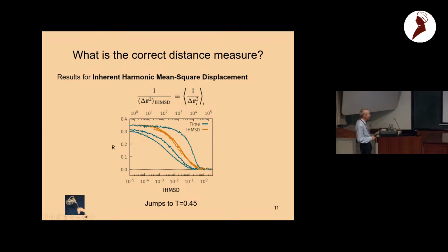And these blue curves are the normalized relaxation functions, and they collapse pretty well if we use this distance measure. There is a mathematical inconsistency in the distance measure, but I don't think it's a serious problem. If you interchange two identical particles, you will get a contribution to this one, but you have no relaxation because they are identical. But I don't think this is a serious problem.